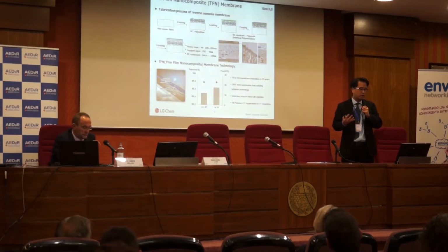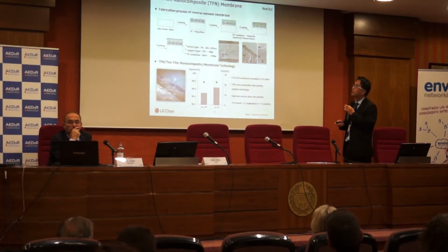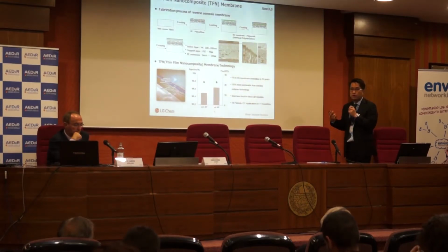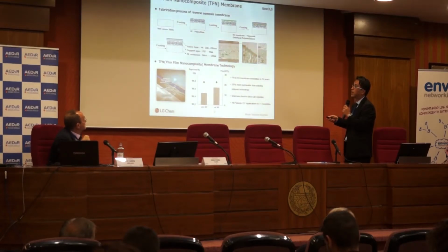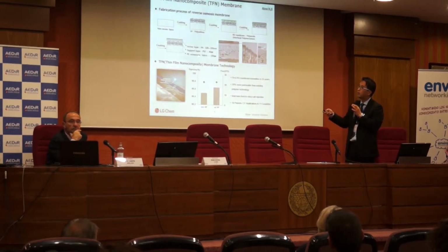How can this thin film nanocomposite membrane get better boron removal? I can explain a little bit of background about our thin film nanocomposite technology and then move on to the explanation of the boron removal phenomena. This is pretty much the standard procedure to make a thin film composite reverse osmosis membrane. You have non-woven fabric, and you have polysulfone casting, and a polyamide layer is coated on top of the polysulfone layer. So most of the membranes on the market have 3 distinctive layers: one is non-woven fabric, a support layer of polysulfone, and then an active layer of polyamide.